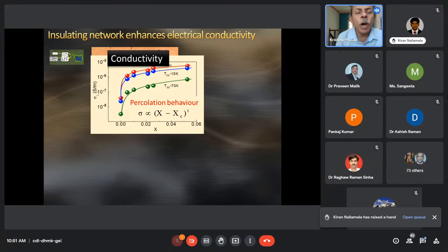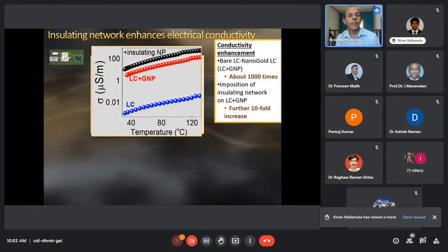So now the interest in this kind of a thing was to confine it in an insulating network, and what will happen to the conductivity of the system dominated by the gold nanoparticles. Because our expectation was, since you are going to put insulating particles, aerosils are insulating particles, into the system, you are anticipating the conductivity to drop in these kinds of phases. But to our surprise, it was to the contrary.